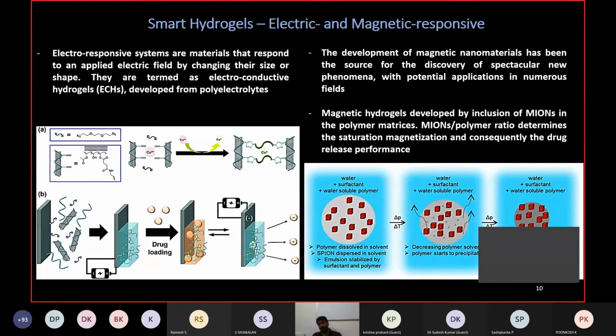And in the other example, where I said polymer coated magnetic nanoparticles, the size of the magnetic nanoparticle is larger compared to the layer of the polymer. They are just used to cover the surface of the magnetic nanoparticle. Here the polymer structure is actually the microstructure we are studying, and the magnetic nanoparticle can occupy some of the spaces. It depends on the mass proportion also. And they are made magnetic, they respond to a magnetic field obviously, so they can be magnetic responsive materials.